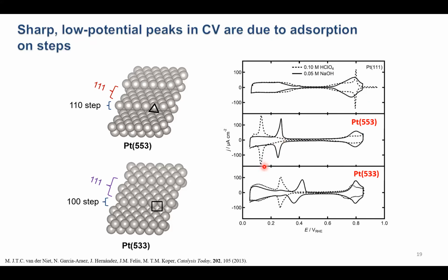Okay, I'll then also briefly mention that in the DFT, we're not going to directly model a polycrystalline platinum surface, and I should say in the experiment with polycrystalline platinum, we don't know what our surface structure looks like. And so to really understand what's going on here, we're going to make comparisons between DFT and measurements on what are called single crystal electrodes. It was measurements on single crystals that allowed us to understand that these sharp peaks measured at low potentials on platinum actually come from adsorption on step sites, because we only see these peaks when we use a stepped surface. And so we're going to use DFT to look at adsorption on the steps and terraces of the platinum 553 surface, as well as on the platinum 533 surface, which have the two different step sites, whose adsorption peaks we were seeing in the polycrystalline platinum.